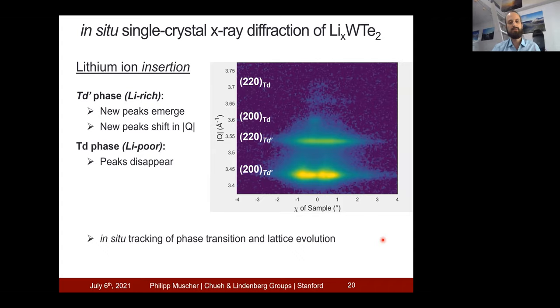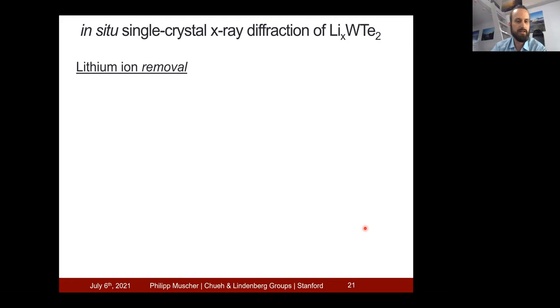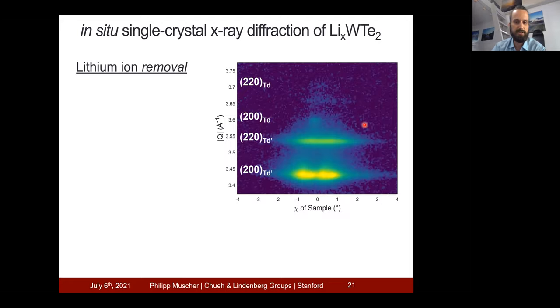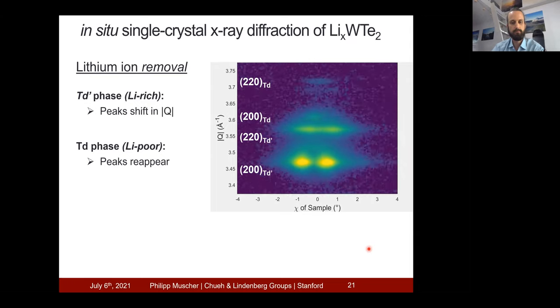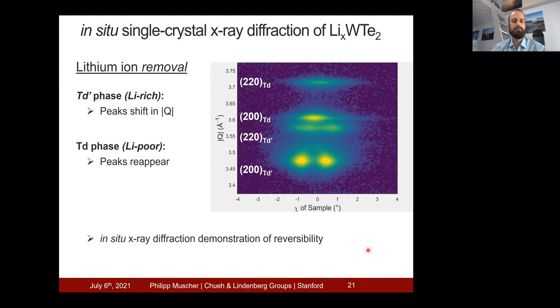So this proves that there's a first order phase transition happening, because the first structure is disappearing at the expense of another structure that's appearing. We can now also look at the lithium ion removal. So we start out with the same diffraction pattern, and now you'll be able to see these peaks shift, become weaker, and the initial peaks reappear. So this shows through in situ X-ray diffraction that the ion insertion is a reversible process.